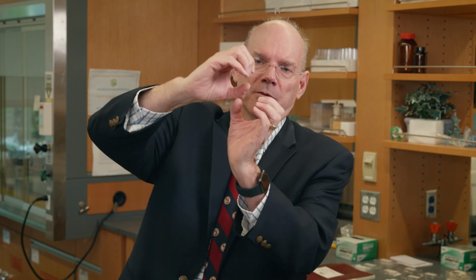Calmetrics had been making chrome calibration standards. These are very thin layers of chromium, and the trick is to make these layers very, very thin, and the way their foils had been supplied was they were made by rolling. So this is a mechanical compression process. You can imagine you had a couple of rollers that are rolling like this, and you've got a chrome sheet that you feed in one side, and the rollers press it down and squeeze it down to make it very thin. And so this rolling process is a standard metallurgical process that's used for lots of different kinds of metals.